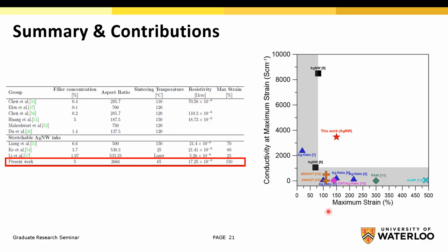So this plot shows the maximum strain and conductivity at maximum strain for state-of-the-art silver nanowire inks, and also for silver flake, polyaniline, gold nanoparticle, and this work. Almost all of the stretchable inks are in this gray shaded area. This gray shaded area means if a stretchable ink has really high conductivity, it can tolerate only really low maximum strain, or if it can tolerate really high strain, it has really low conductivity.